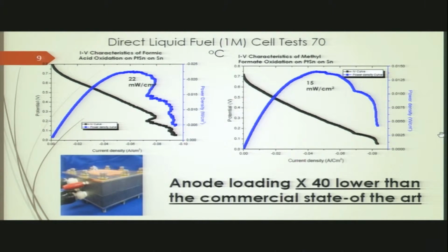We used it with synthetic fuels, with formic acid and methyl formate, and we were able to show an improvement of 4x over the state-of-the-art platinum ruthenium. And recently, we've even used it for dimethyl ether and showed also very significant improvement in performance.